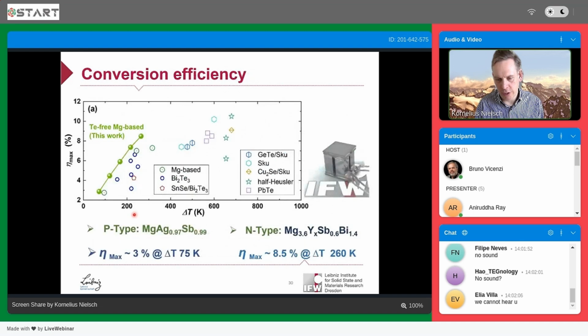So when I bring all these improvements together, in principle the three improvements: using yttrium as a dopant, improving the compaction process, and also optimizing the geometry by having a denser thermoelectric module, we obtained in total a maximum thermoelectric efficiency of 8.5%, applying a temperature gradient of 260 Kelvin.